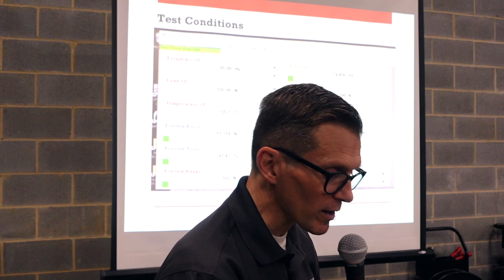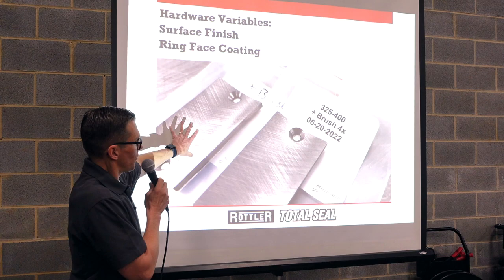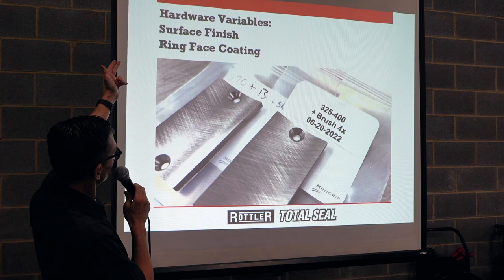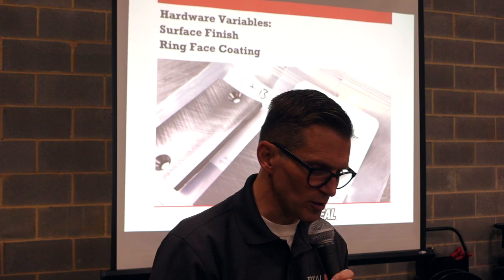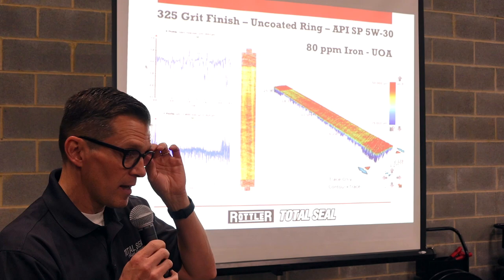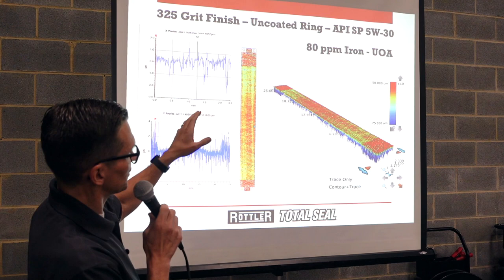Like I said, we can actually see these pieces here where we've honed those sections of liners, different finishes. From the hardware side, we can change the surface finish, we can change the ring coatings, and we can also change the oil. So we began with a baseline 325 grit, that's a 325 diamond, with an uncoated ring using just off-the-shelf API oil, just regular old stuff.